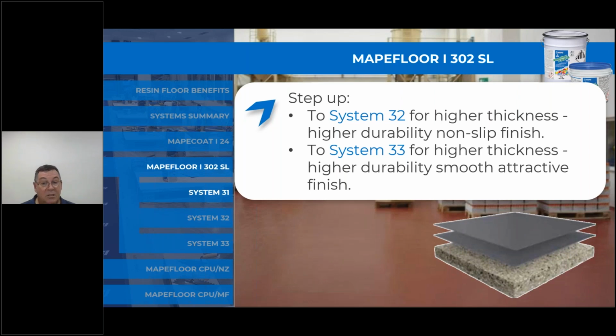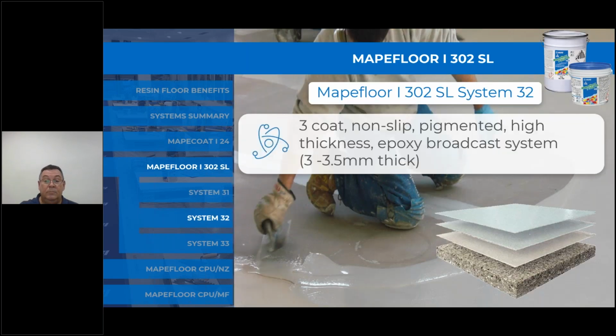We step up from there to the System 32, which is a much higher thickness and a higher durability, non-slip finish. And then from there, we also go to System 33, which is a much higher thickness, high durability, smooth, attractive finish. So you have the option of a slip resistant or a smooth, self-leveling floor system from this product. So the I-302 SL System 32, it's a 3-coat, non-slip, pigmented, high-thickness epoxy broadcast system, generally 3 to 3.5 or 4 mil in finished thickness.